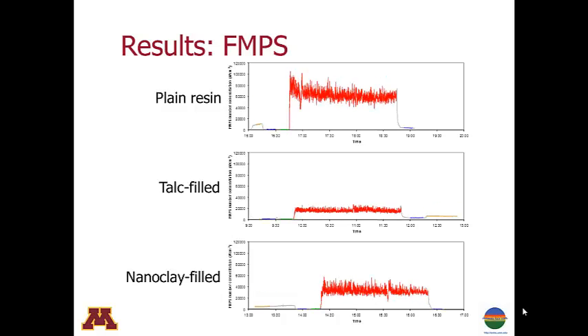Particle number concentrations can be calculated from the fast mobility particle sizer data by summing the particle levels measured in each size interval. We found higher concentrations from the FMPS than from the P-track. Because the FMPS measures particles with diameters down to 5.6 nanometers, whereas the P-track only measures particles down to about 20 nanometers, the higher levels seen in the FMPS data indicate that many particles smaller than 20 nanometers were generated when the test plaques were shredded.